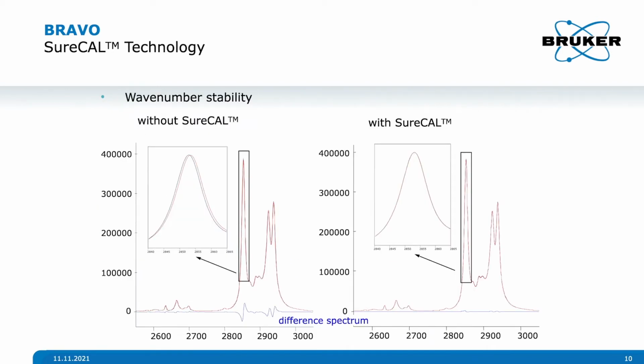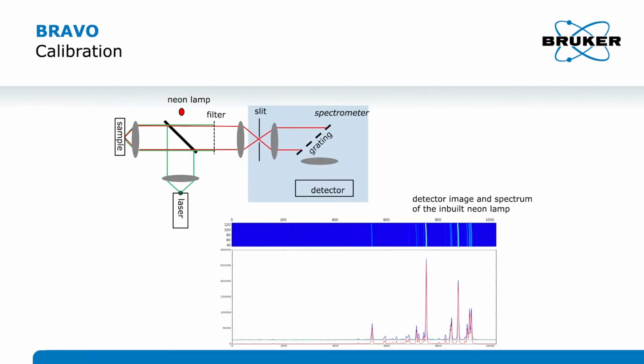Here's a good example of where we're doing the subtraction on the left without the SureCal and on the right with SureCal. And you can see how nicely we get rid of any artifacts that might be there with any drift in the wavelength precision over time. And that's due to the active control of the laser, and we also constantly monitor the laser. So this is how the calibration works for the Bravo. We have a built-in neon reference lamp, which is patented by Bruker to use as a calibration standard inside the spectrograph. And then we monitor the emission from the neon lamp all the time with the Raman signal, such that the wavelength is calibrated to the best possible wavelengths.